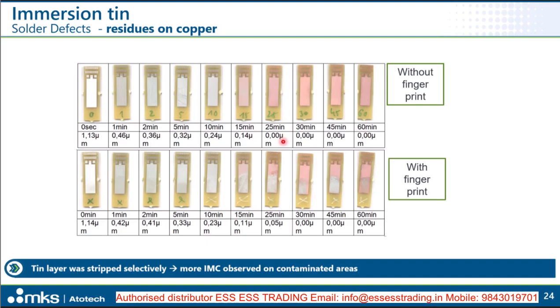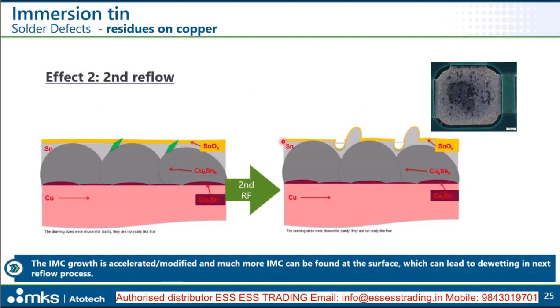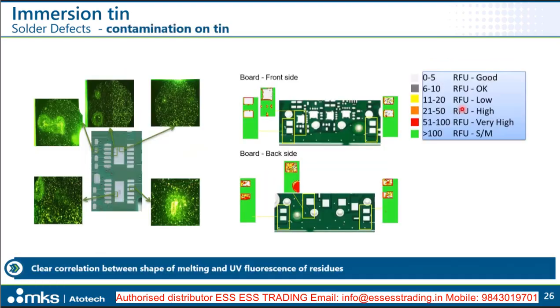So what is the meaning? It means that where we have contaminations, different, stronger IMC is formed compared to a clean surface. And this for sure can then have an impact in the second reflow cycle, because then the IMC grows further. And if we have contaminations here, these may attack or destroy the tin oxide layer, and in these areas the remaining liquid tin comes through the top and then forms these inhomogeneities and dark areas on the surface. So this is something which we would like to prevent.